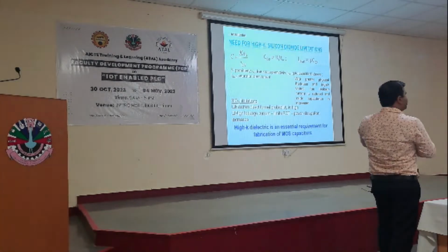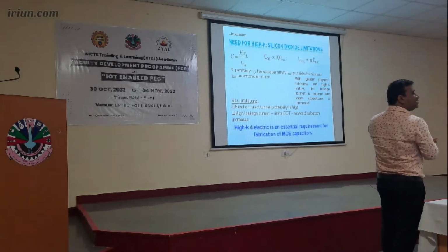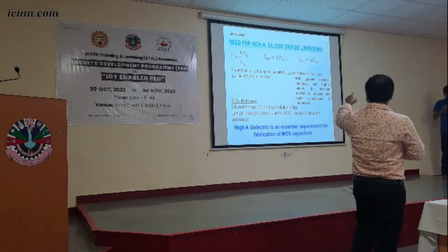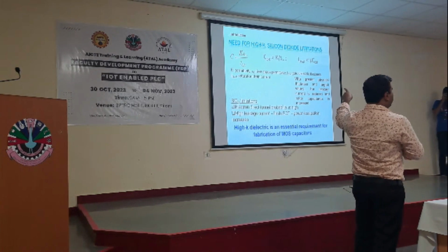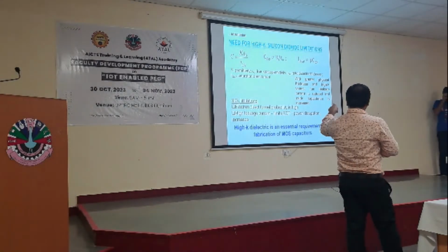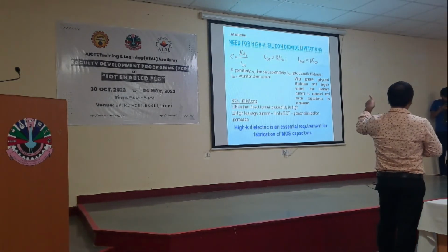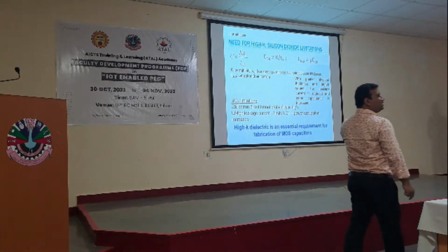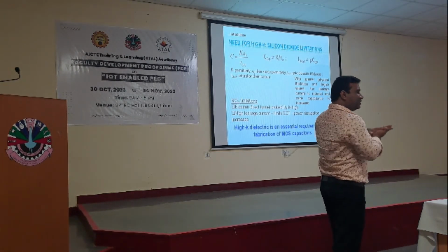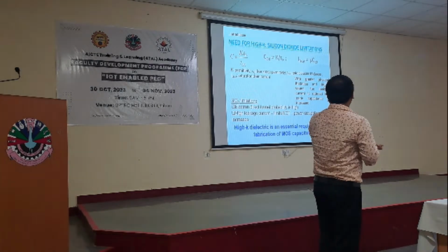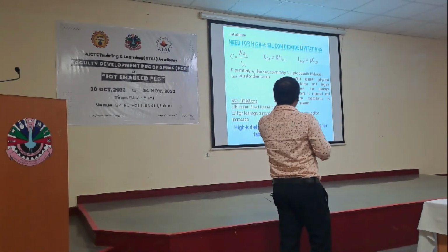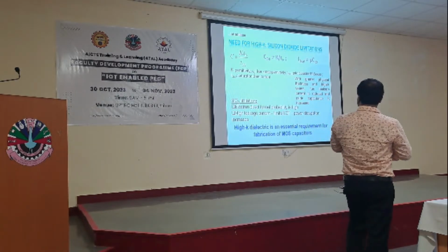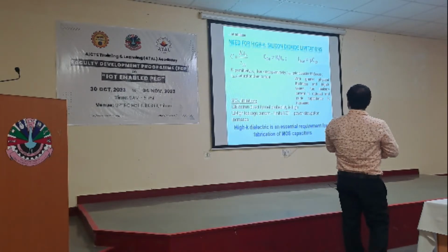If you take a very thin material, your leakage current density will be very high. That is undesirable. That's why the only option is high K. If you take a material with a very high dielectric constant, your capacitance will be higher, because your target is to get high capacitance in a silicon based MOS capacitor. Now, SiO2 also has limitations.